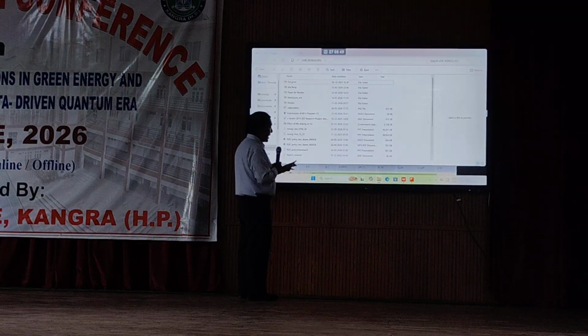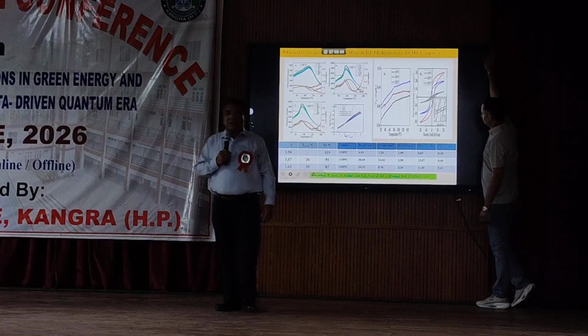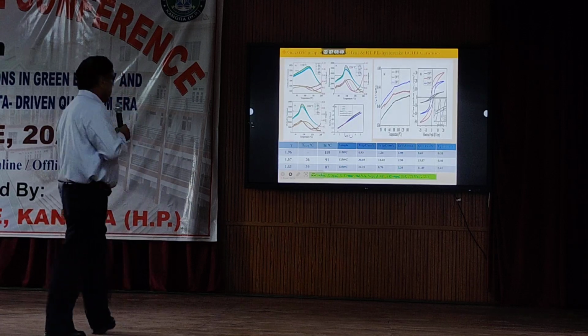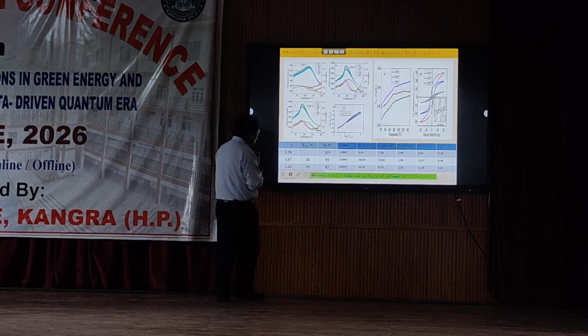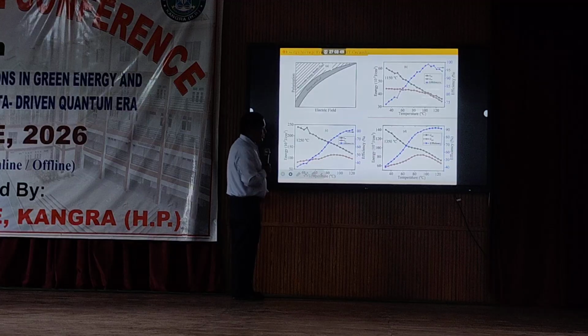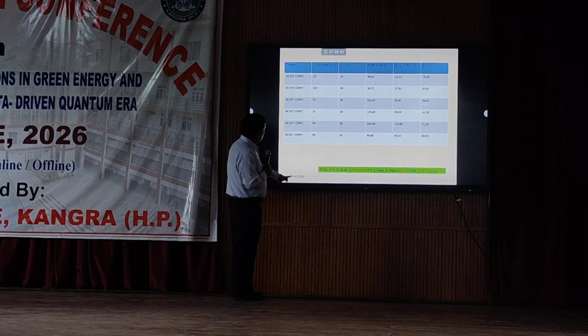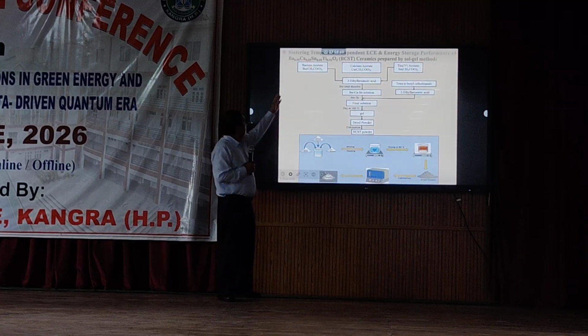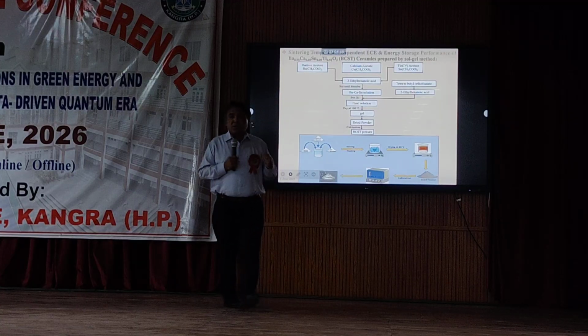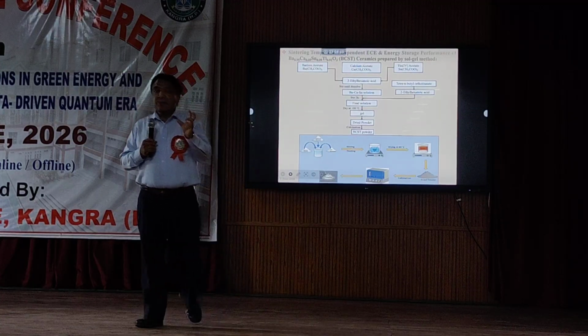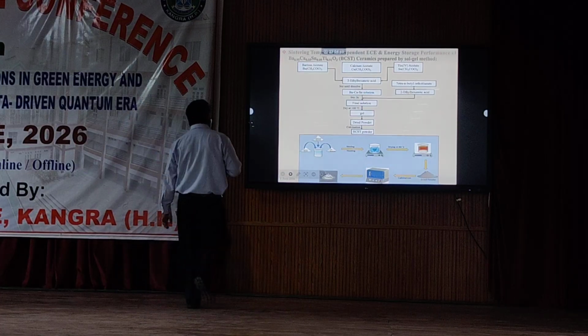And here again, we observe a similar kind of reverse characteristic, that higher efficiency can be achieved at the cost of low energy density. So I want to show one more result, that is Sm doped, so as to realize what we have discussed till now. So this one, that is Sm substituted on the titanium side, again a morphotropic phase boundary, where one can see that morphotropic phase boundary in a clear way in the dielectric property.